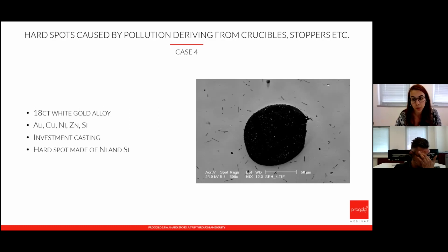What happened here is that at ProGold, we always use graphite crucibles to produce, and we have tested all the products that we sent out in our laboratory, and we didn't have any issues. At some point, a client came forward and said, okay, look, I'm having this issue. We started investigating, and it turned out that this person was using silicon carbide crucibles. The silicon carbide was releasing silicon inside the alloy, and we were increasing the quantity of silicon inside. At a certain amount, the silicon decided that it was better to react with the nickel and form this nickel silicide compound that you're seeing here, instead of remaining dispersed inside the melted alloy and doing the function it was set to do.